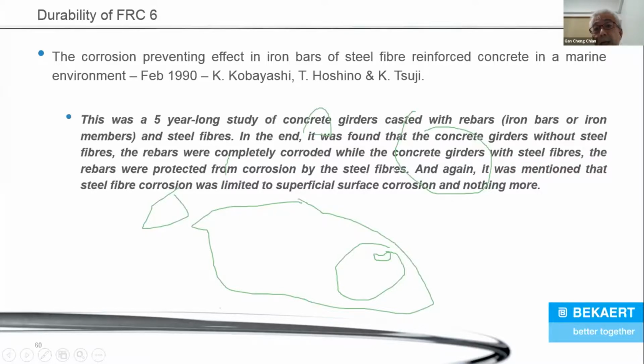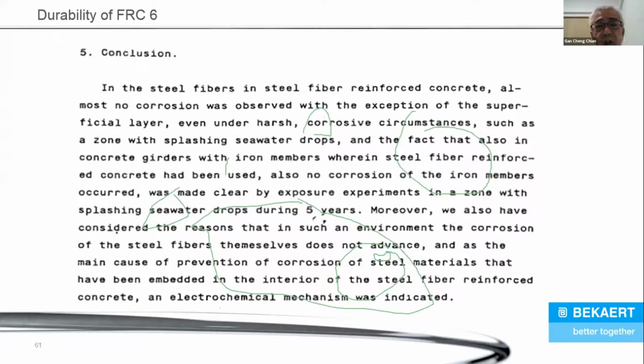This is amazing information, but it was already published in 1990, just that nobody knows about it. And again, it was mentioned that steel fiber corrosion was limited to superficial surface corrosion and nothing more. And this test was done in a marine environment, so it's very stringent, a very high salt, high chloride marine environment. So this is the extract of the conclusion from that paper. And again, if you need the full paper, you can just ask for it and I will definitely send it to you.